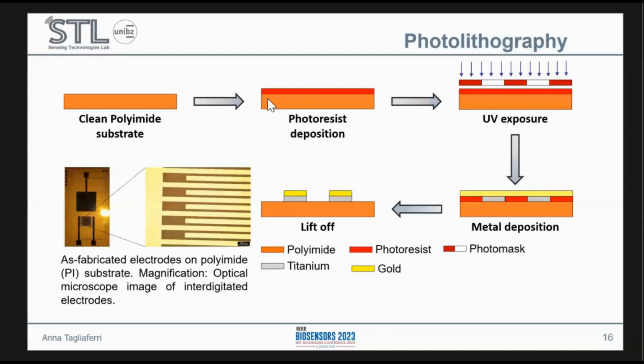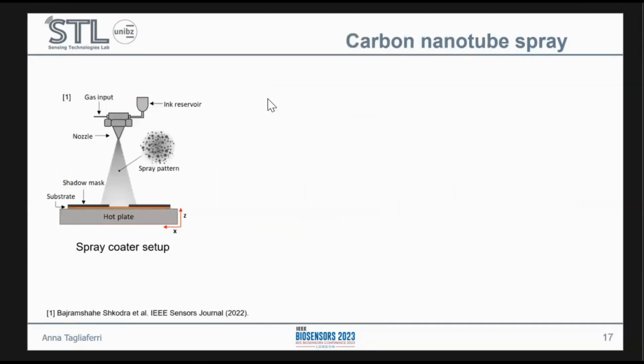Here, magnified, you can see just the detail of our interdigitated electrodes, where we sprayed the carbon nanotubes. This was our setup. The process was previously optimized since we had already several examples of carbon nanotube electrolyte field effect transistors. And we set the hot plate to 70 degrees Celsius. We set the distance between the substrate and the nozzle fixed at 5 centimeters, and the speed at 150 millimeters per second.